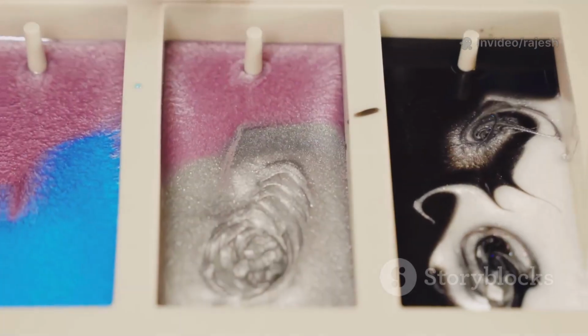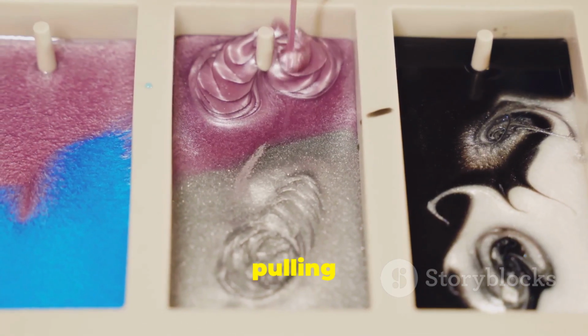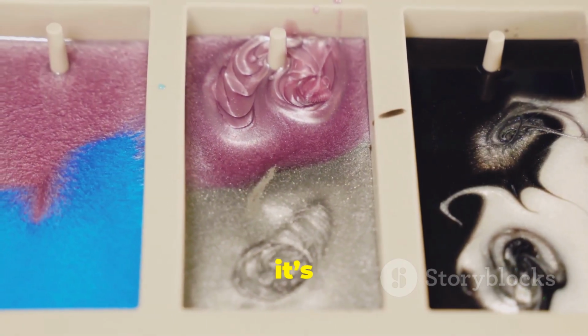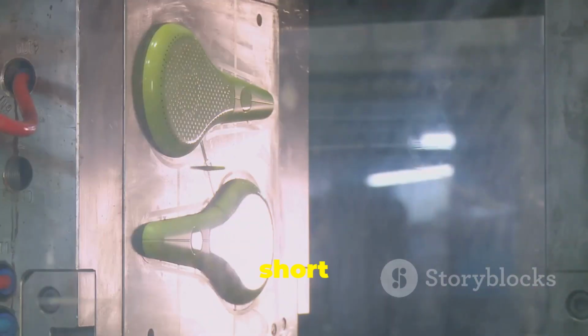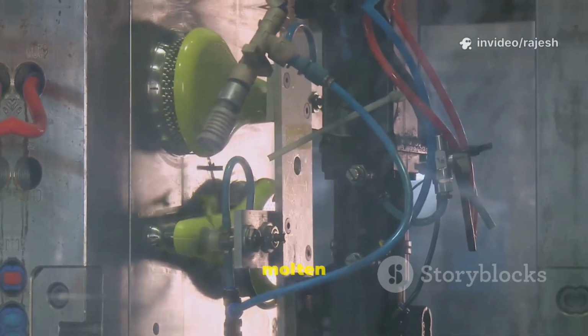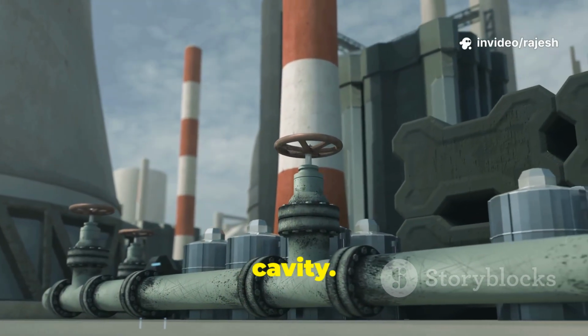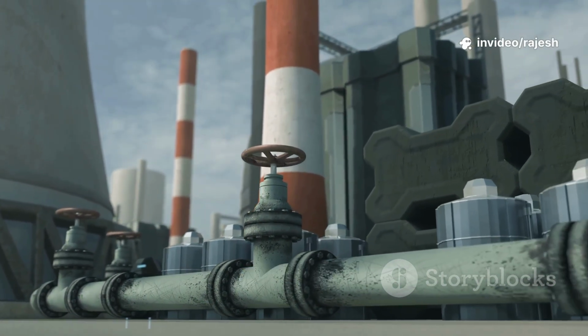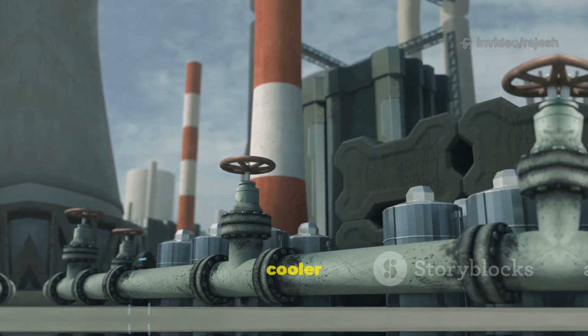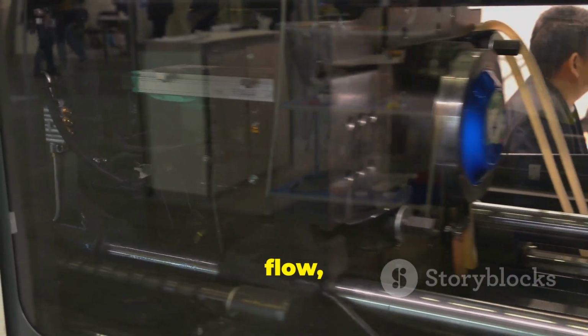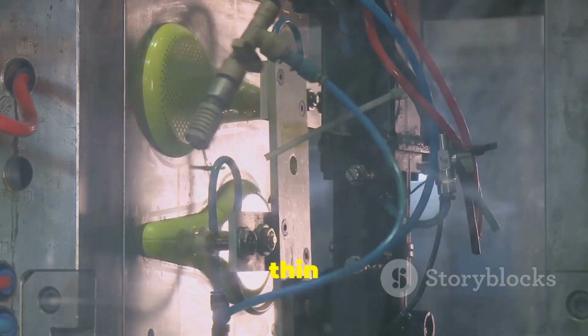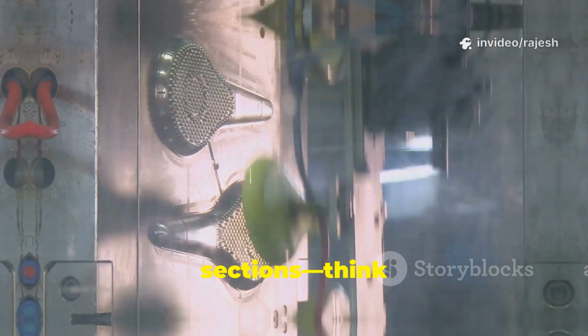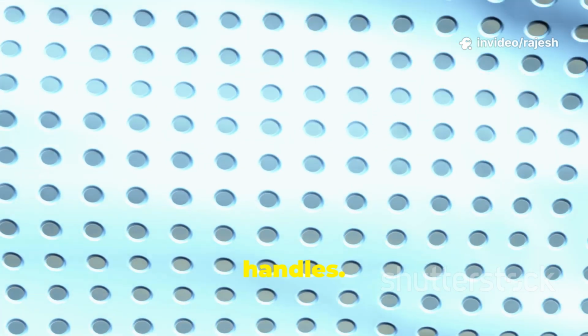If you're an engineering student, this is for you. Let's jump in. First up, imagine pulling a part out of the mold, and it's only half there. That's a short shot. This happens when the molten plastic doesn't fully fill the cavity. Main causes: low injection pressure, a cooler melt, poor material flow, or blocked gates. I've seen this pop up most often in thin or super long mold sections. Think battery covers or long handles.